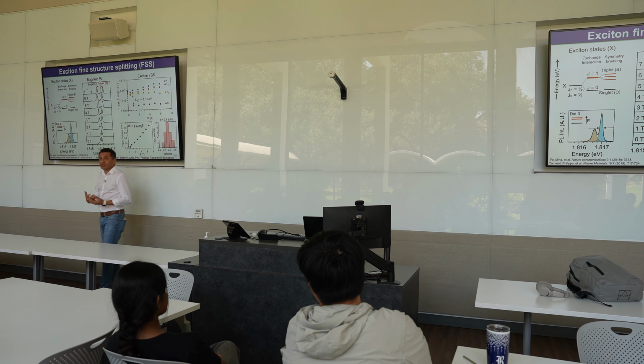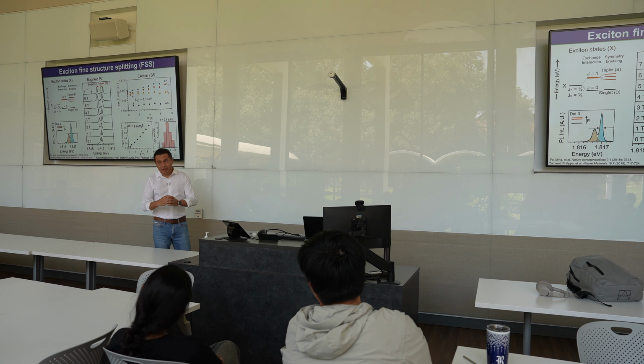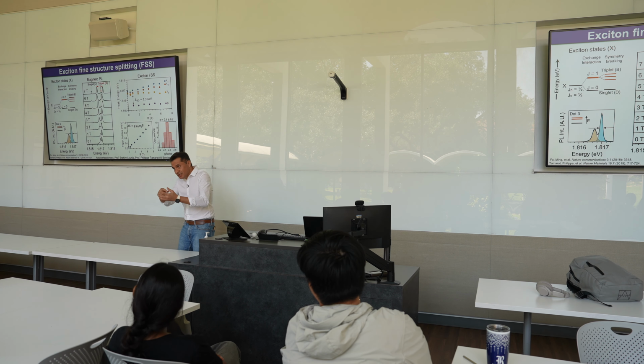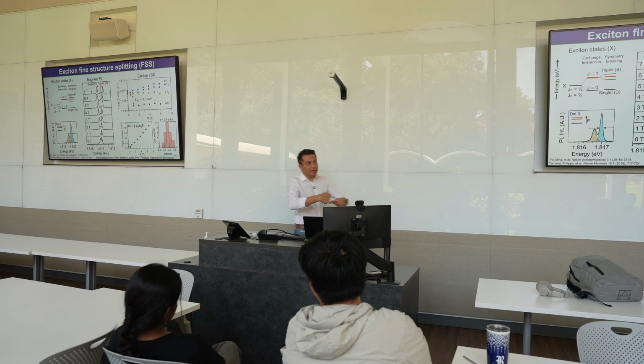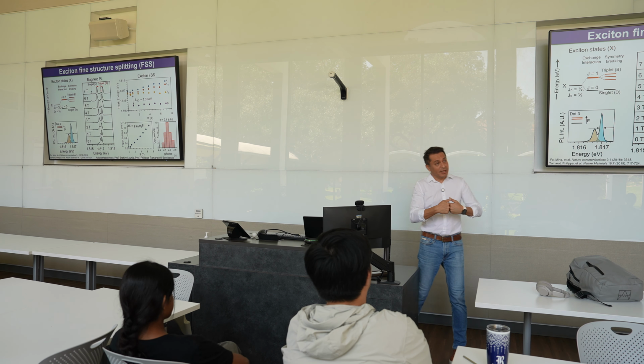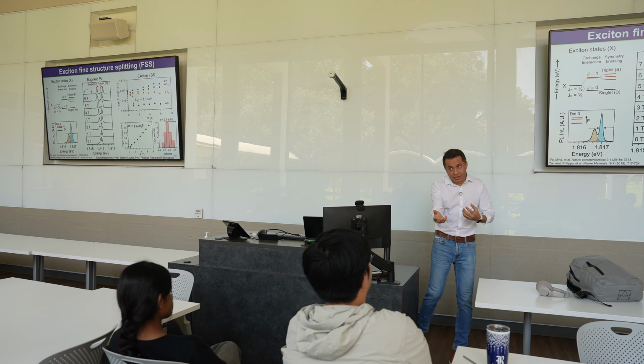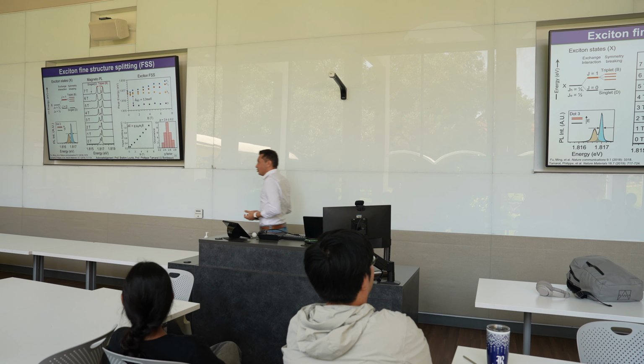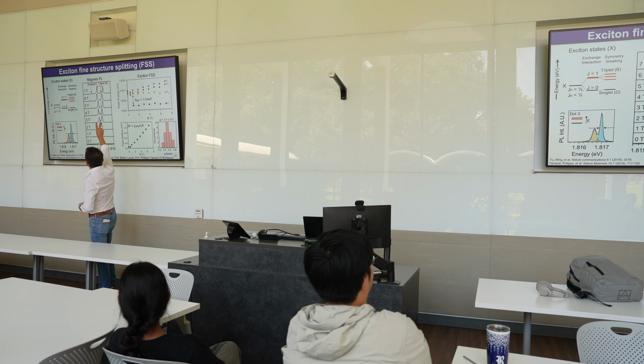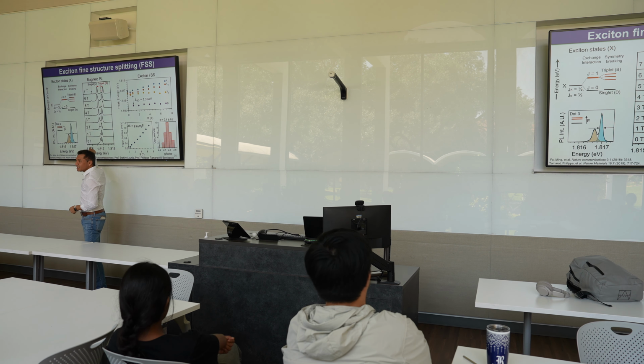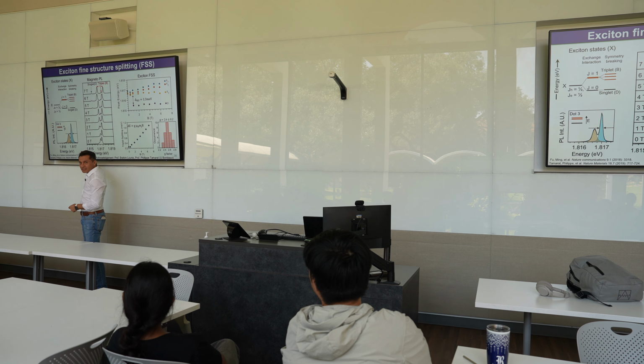And this is actually a triplet state because the quantum dot is not perfectly spherical. The structural symmetry is broken, and even within the atomic scale, it's tetragonal, it's not cubic. So you break that symmetry and you get the triplet state, which becomes the really dominant emission state. And then I can apply magnetic fields. You see this beautiful Zeeman splitting. But you also see that the singlet state, the dark exciton, starts to become allowed now.